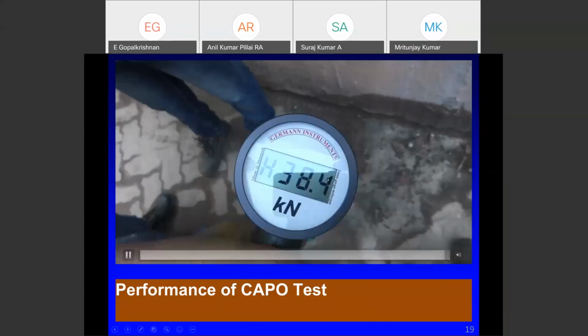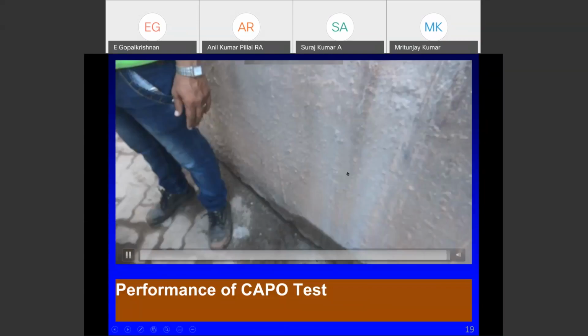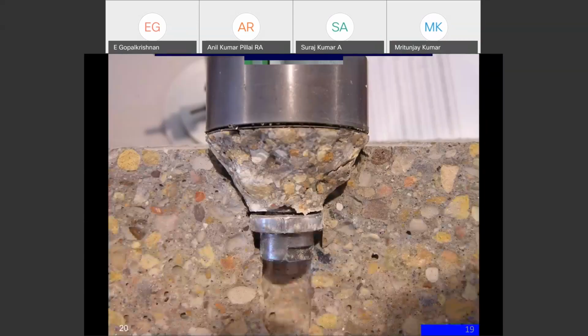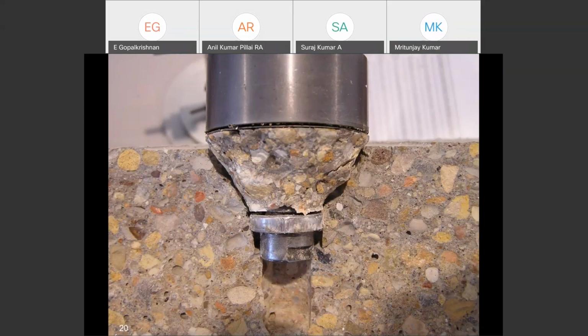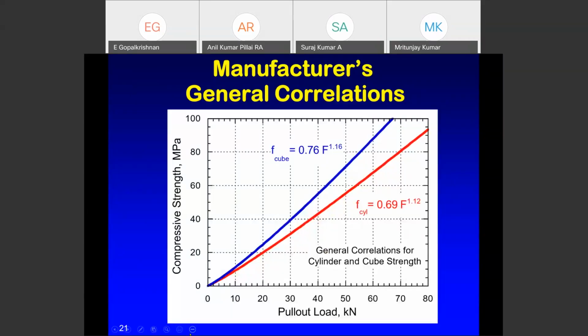Now I am going to tell you how to interpret this force, 38.4. Here I can show you the damage is a V cone shape that we have taken out from this pull-out test. There is a curve provided. We can say this is a correlation curve. The red indicates the cylinder and the blue line indicates the cube. If you say 30 kilonewton, it's around 40 MPa as measured from the curve.